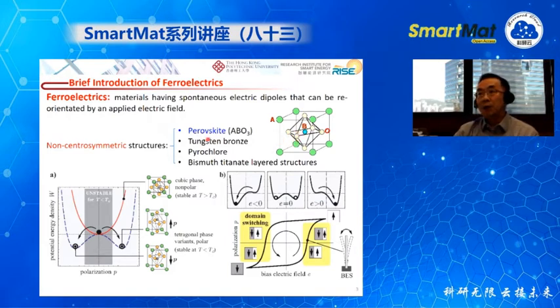So normally the perovskite structure at a high temperature carries a cubic structure, and the positive ions and negative ions have their centers located at the same position. So at a high temperature, there's no spontaneous polarization. However, when the temperature is lowered below the Curie temperature, there is off-center displacement between the positive ions and negative ions. So a net spontaneous polarization is generated. And we can use the Landau phenomenological theory to explain these phenomena.